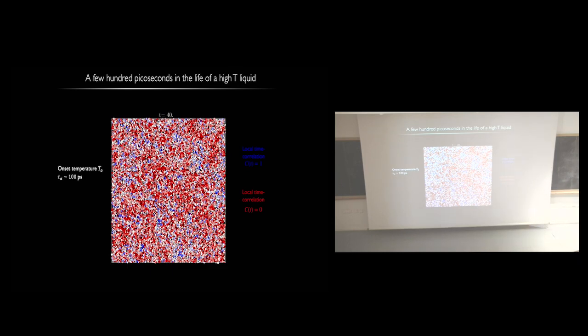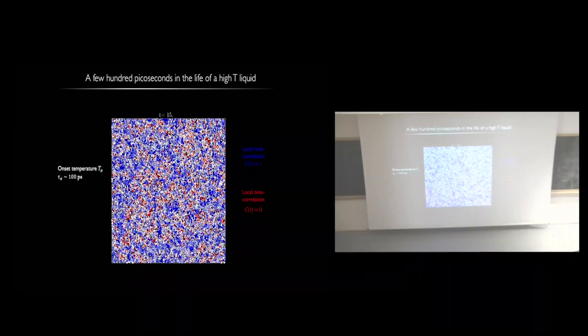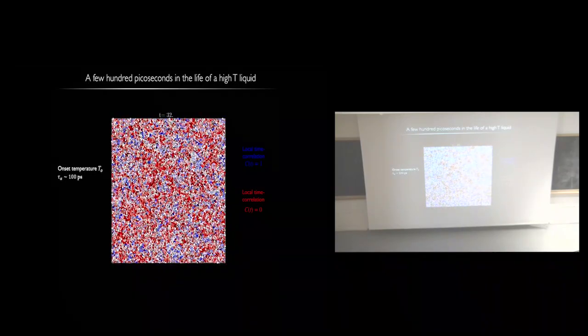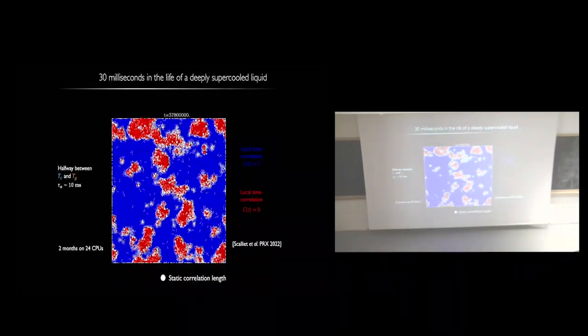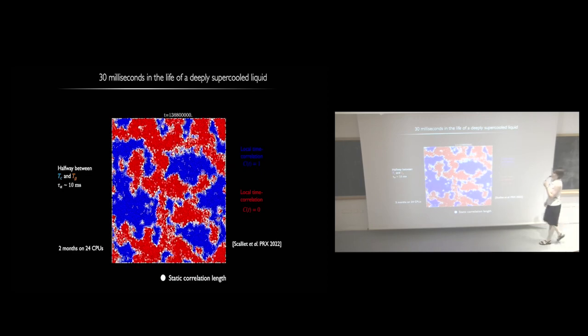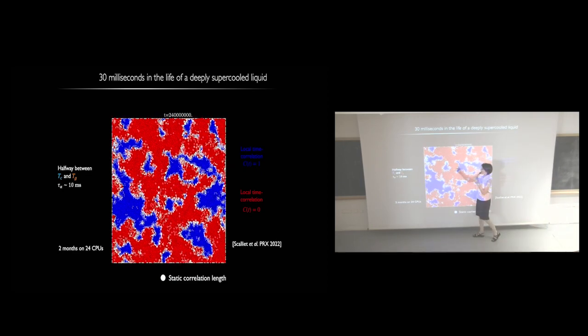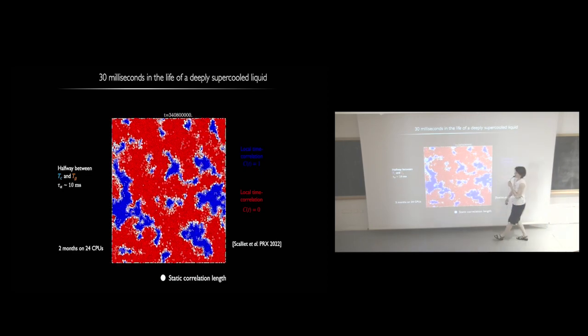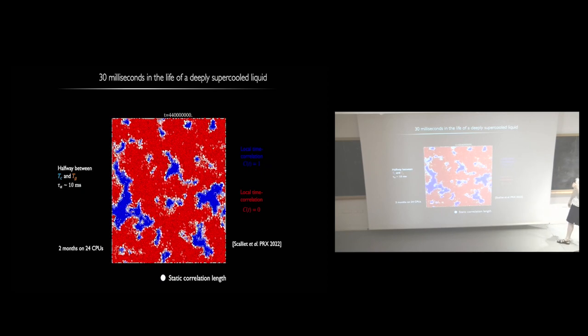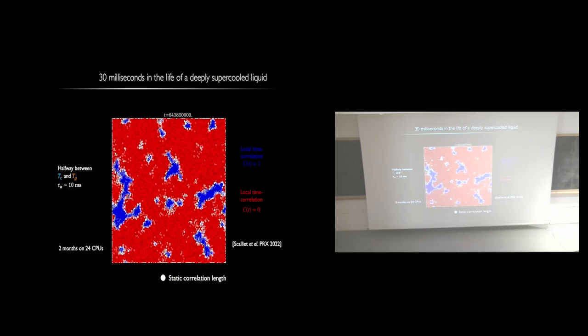You see at high temperature, there's no real clear correlation, or the dynamic length is very small. But if we go to a regime that was not accessible before, then you really start to see the emergence of these correlated dynamical regions. Okay? This is what we see, and it's nice because now we can really observe the dynamics in this regime.